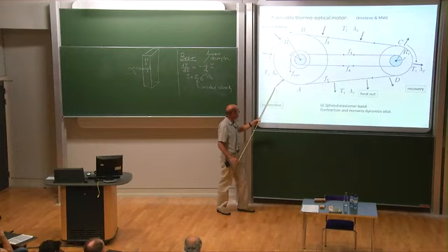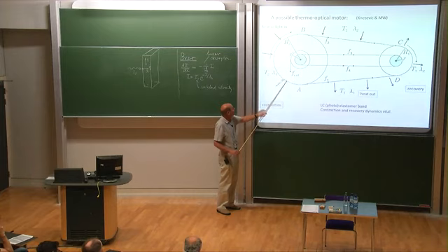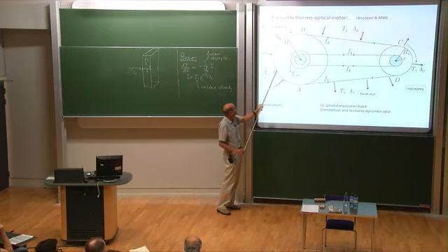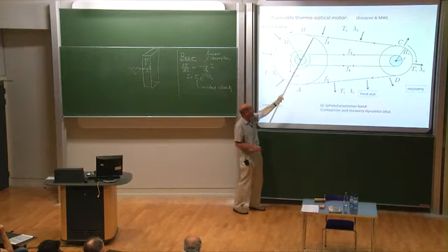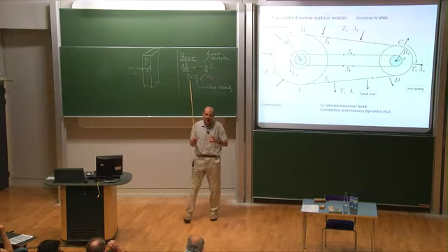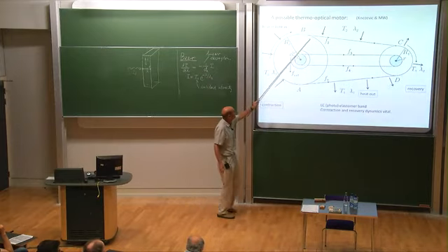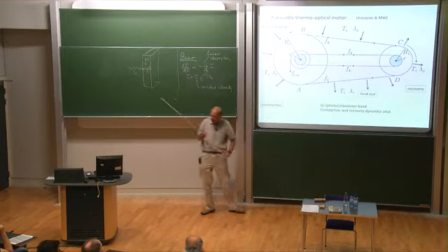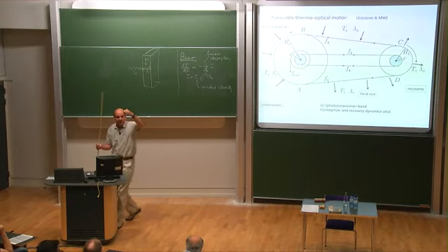So where it is receiving light, its natural length decreases, its actual strain doesn't change because it's in contact with the wheel, so a big tension arises, and it's only here that it becomes free, establishes a new equilibrium stretch, and the tension is realized.